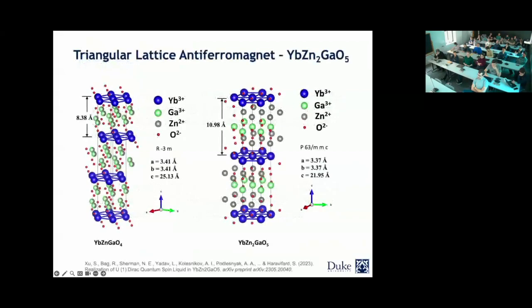This is the 1114 compound which we've just discussed, which has the chemical disorder between gallium and zinc. Here you have the triangles with ytterbium 3+, and this is the chemical disorder between gallium and zinc. You can see it has space group R-3m. This is the distance between the two magnetic layers, and A, B, and C are the lattice parameters.